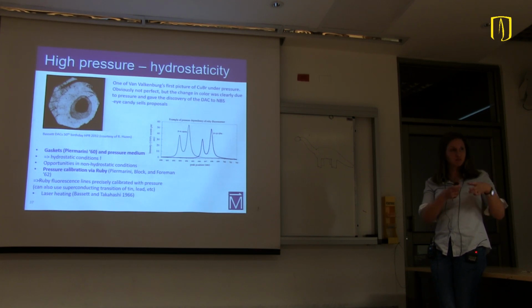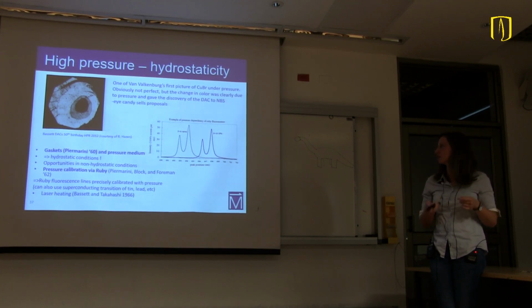A gasket is literally a gasket, a joint, where you put that around your anvil, you put a pressure transmitting medium, and you go basically from crushing your sample to developing a hydrostatic condition around your sample. And that was a revolution for the field of high pressure.